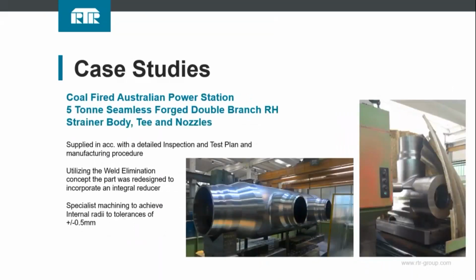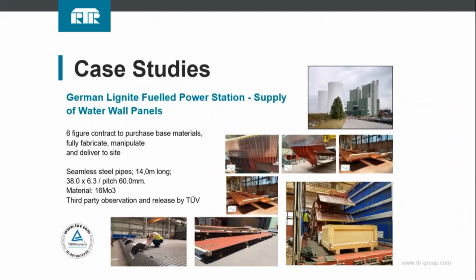This is one of the largest forgings that we've produced in our company. You can see this double branched 5-ton reheater strainer body, the machining involved to produce the finished part, produced with an integral reducer, eliminating the weld setup that was previously in place. And this is all manufactured to extremely tight tolerances, plus or minus half a mil to manage weight. And also there's been thousands of dollars spent on the technology to machine the internal radii on products like this, smooth and completely contoured to eliminate those stress points of sharp edges that you see.